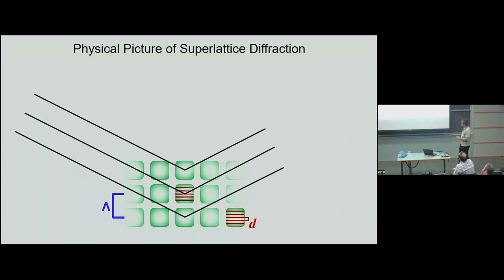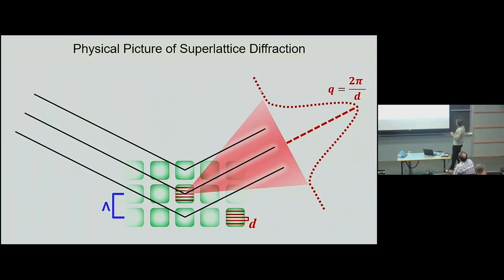Over time, we improved our understanding of this effect. Here's its physical picture shown diagrammatically. Incident X-rays are first diffracted by the atomic planes of each nanocrystal, producing a Bragg peak at a certain Q position, which is broadened due to the finite size effect. Then, because of the secondary periodicity lambda, there is an additional phase shift that produces secondary interference with the spacing according to the superlattice constant.